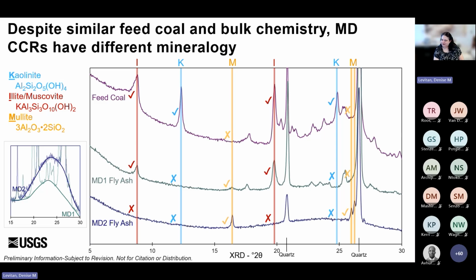And then we start to see maybe a little bit of this peak here in the MD1 fly ash, though we don't see those double peaks here. And then by the time we get to the highest temperature, the MD2 fly ash, we do see a distinct peak at both this location and then this double peak here, indicative of the presence of mullite, which forms around 1100 degrees Celsius. So what we see here is a thermal transition going from the feed coal with really minimal heat, and then up to the 900 degrees-ish of MD1, and then the 1300-ish of MD2, and different minerals present with that thermal transition at each or within each.